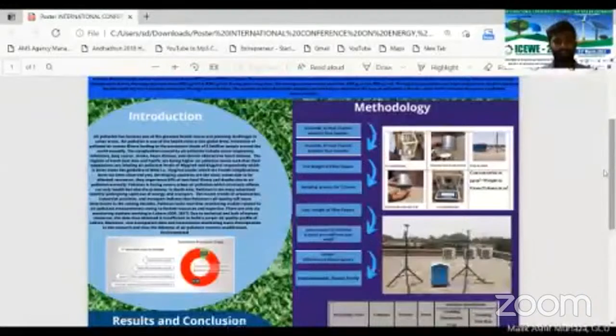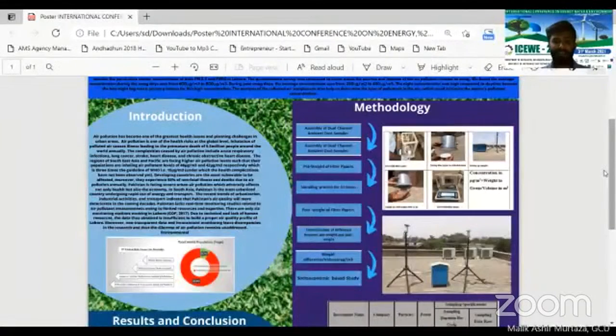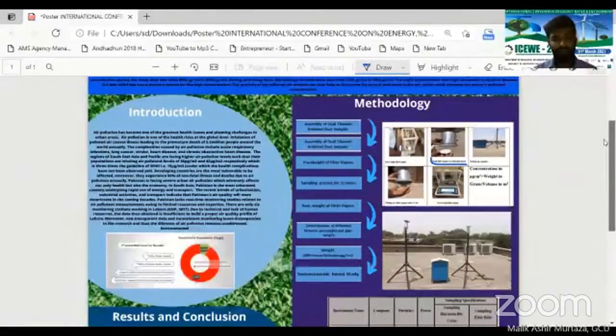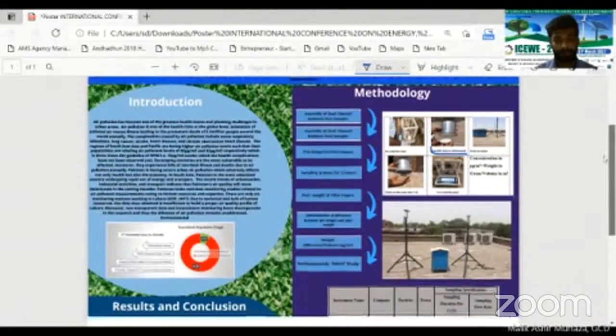The research was conducted at the SDSC Department, GC University, Lahore. For this, we used the dual dust air sampler that was manufactured at the lab. First of all, we used gravimetric analysis for conducting this research. We pre-weighed the filter papers, then placed them in the filter assembly as shown in this picture here, and after a 12-hour cycle, we take the filter out of the filter paper assembly and then post weigh. The difference in the weight gives us the concentration of the particulate matter.